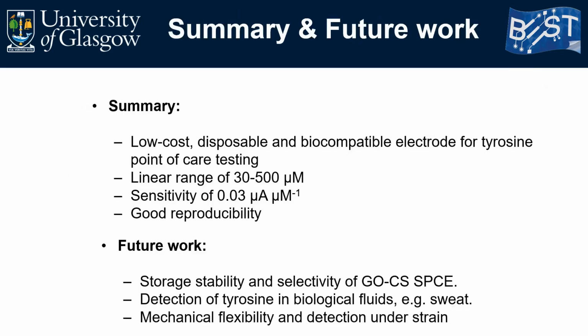To conclude, this work has demonstrated the facile development of a tyrosine point-of-care testing device, based on a low-cost, disposable and biocompatible graphene oxide Chitosan modified screen-printed carbon electrode, supported by a flexible PVC substrate. The graphene oxide screen-printed carbon electrode demonstrated a wide linear range of 30 to 500 micromolar, with a sensitivity of 0.03 microamps per micromolar and good reproducibility.